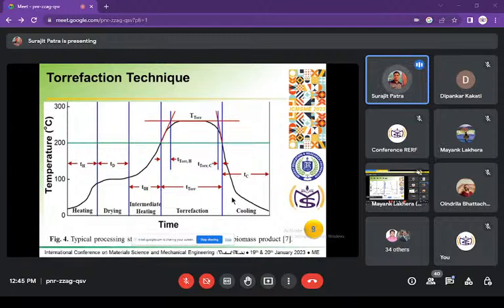This figure indicates the change in biomass color and the chemical reactions that happen in the biomass at different temperatures and in the different thermal pretreatment processes. We see heating, drying, intermediate heating, torrefaction, and cooling. The curve shows each and every step. It describes the temperature zones: first the non-reactive zone, 50 to 150 degrees centigrade, the second is the reactive zone, 150 to 200, and the third is the destructive zone, 200 to 300 degrees centigrade.